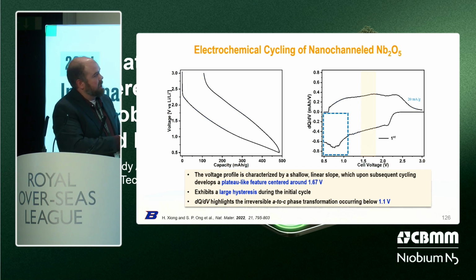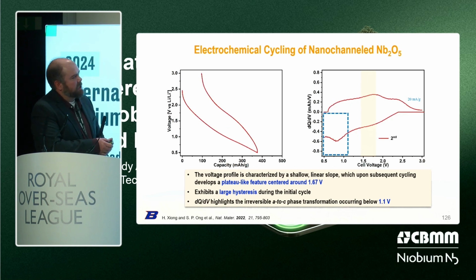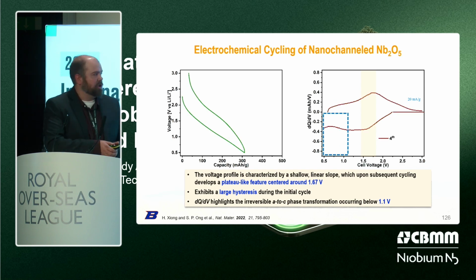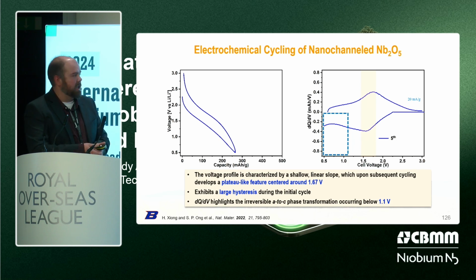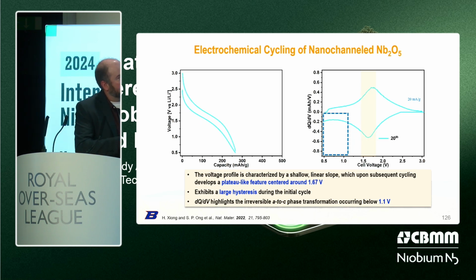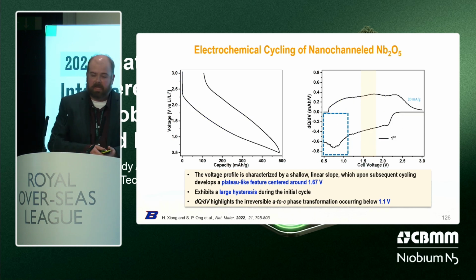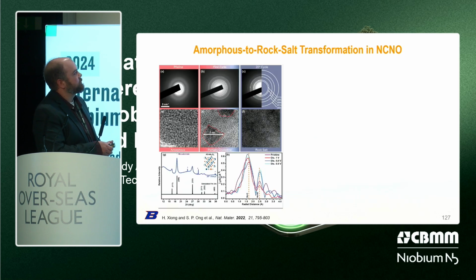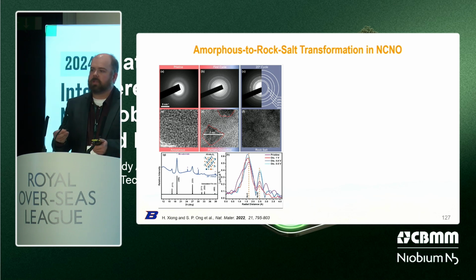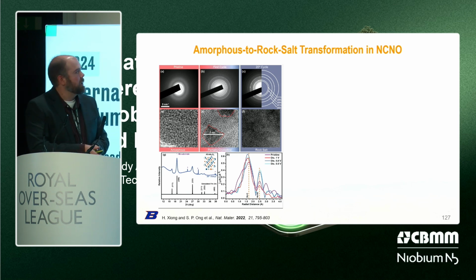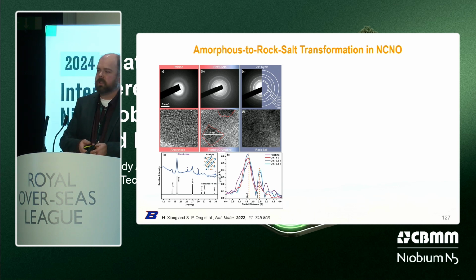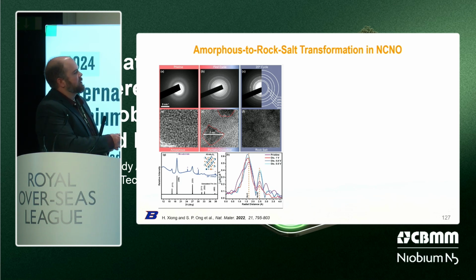What's happening here is that this large hysteresis is associated with the phase change at that low end, while we're inserting lithium into the niobium oxide, and observing this amorphous to cubic phase transformation below 1.1 volts. In our pristine material, we have purely amorphous niobium oxide. On the first cycle, we start to see nanocrystalline rock salt niobium oxides forming within the material. And by the 20th cycle, we were no longer able to see any amorphous material. And it was confirmed by